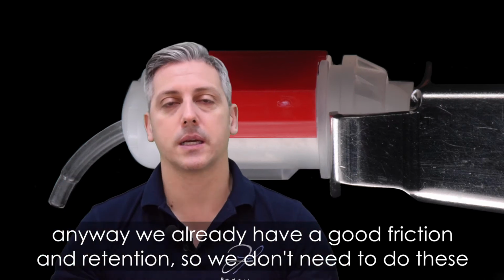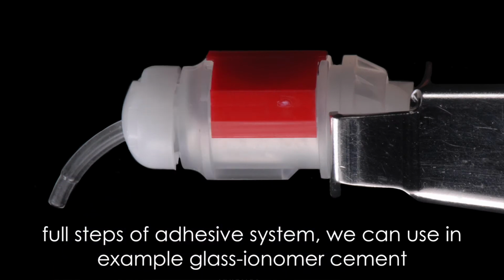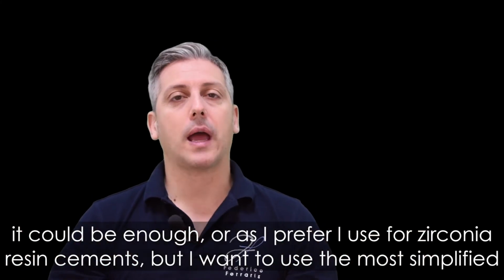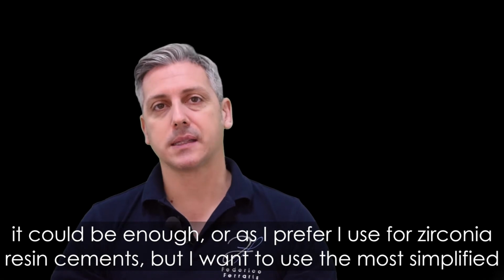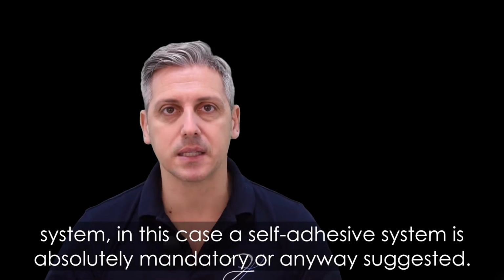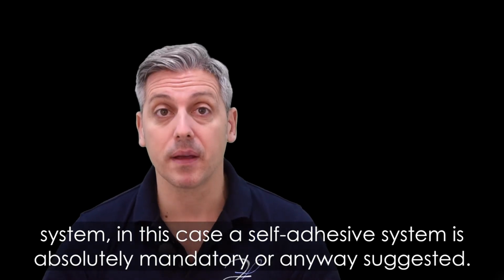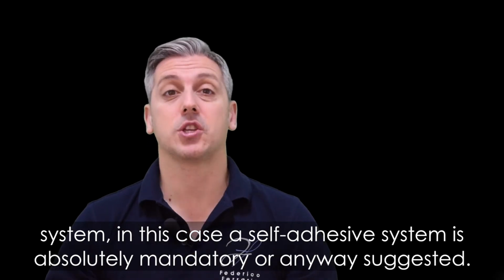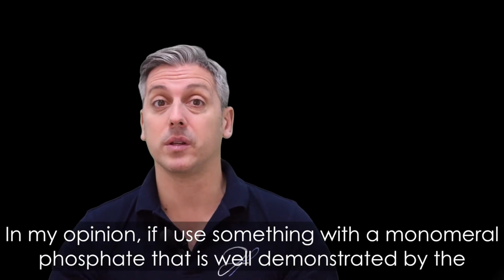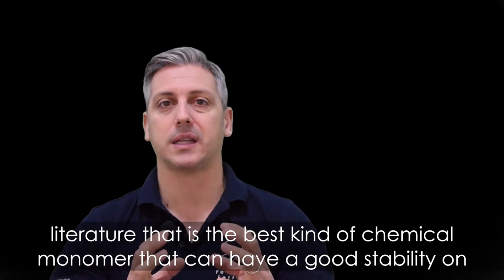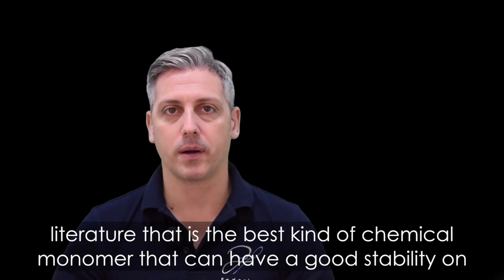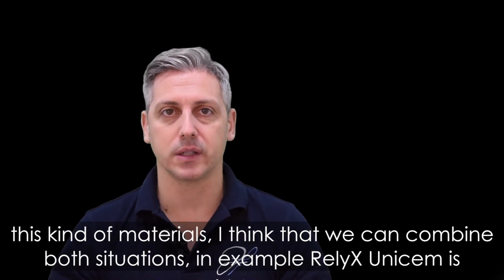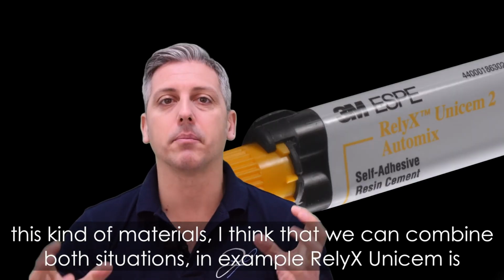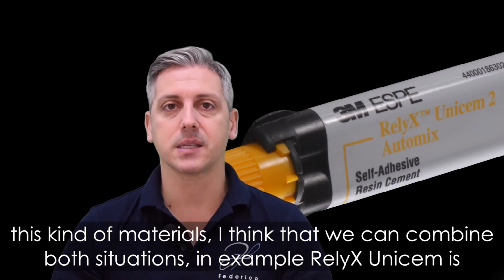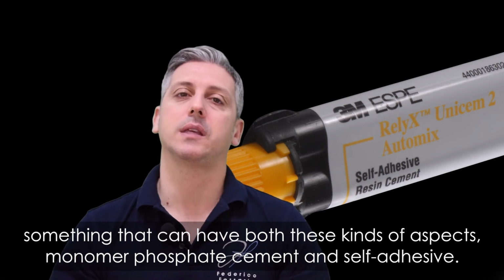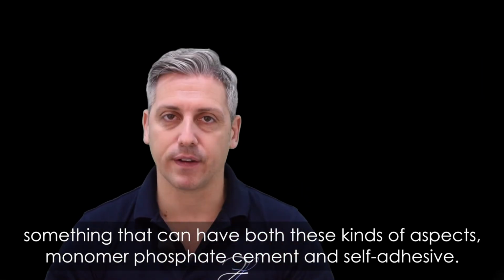So we don't need to do the full steps of an adhesive system. We can use, for example, glass ionomer cement, which could be enough. Or, as I prefer, I use resin cements for zirconia, but I want to use a more simplified system. In this case, a self-adhesive system is absolutely mandatory or at least suggested. In my opinion, if I use something with monomer phosphate, which is well demonstrated by the literature to be the best kind of chemical monomer for good stability on this kind of material, I think we can combine both situations. For example, RelyX Unicem has both these aspects, a phosphate monomer cement and self-adhesive.